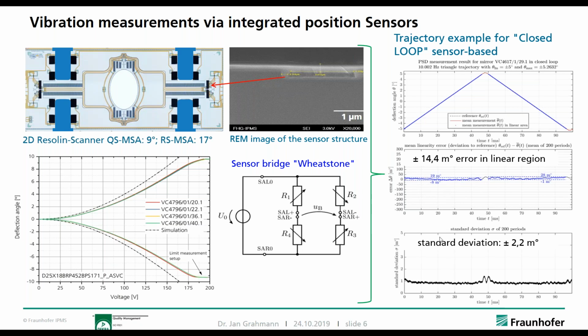So in these two graphs below, you see the deviation, and there we have two parts of it. One is an error in the linear region. That means this error shown here is systematic. So for each scan of that triangular trajectory, you will have the same deviation of the linearity. So it is reproducible, and depending on the application, you can compensate it. And that is in the range of 14 millidegrees error for that scanner.